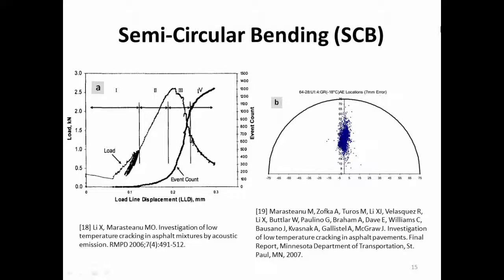Fracture mechanics originated from good materials, nice pure materials like metals, so it's easier to study. But for asphalt mixture, we know that they have aggregates, binders, and voids. So the behavior in front of the crack tip is not the same situation as we described for metals. So people think, how does the crack grow in these asphalt mixtures? They put acoustic emission sensors in these samples and then do the entire test. This is a load-displacement test. If there's one micro crack, they will count once. So basically this tells us how many counts they get for this entire process.